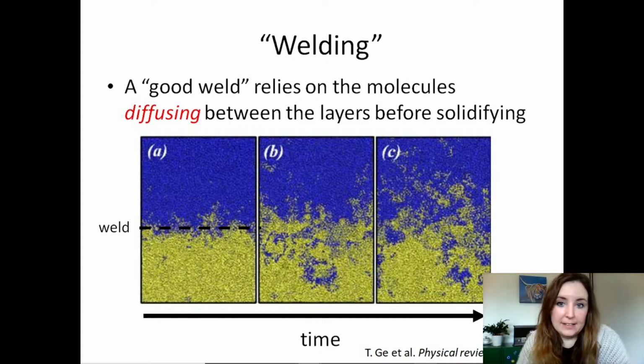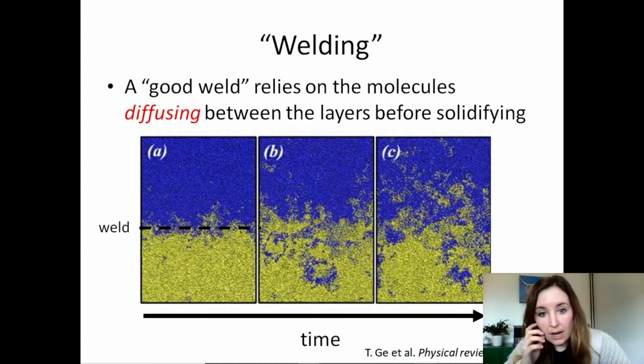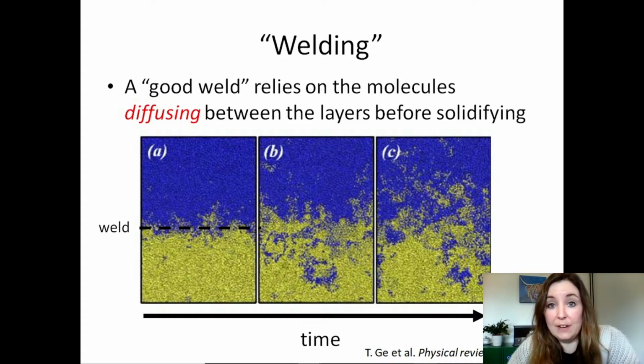So this is a molecular simulation of this welding process. The idea is you bring together a yellow layer and a blue layer and you leave them for a certain amount of time, and you can watch how the yellow molecules interdiffuse into the blue molecules and how the blue molecules interdiffuse into the yellow molecules. You can see as time goes on, the further they're able to travel across that interface and the better the weld becomes. If you had an infinite amount of time, then this interdiffusion process would eventually completely erase the weld line, so there would be no memory of there ever being a separation between the yellow layer and the blue layer.